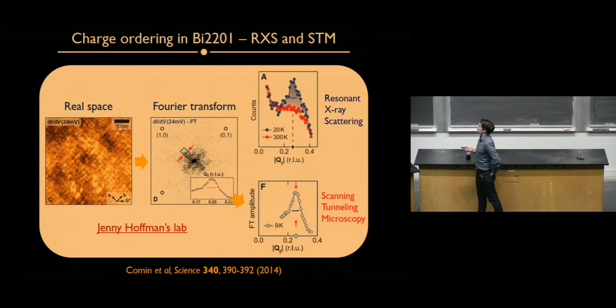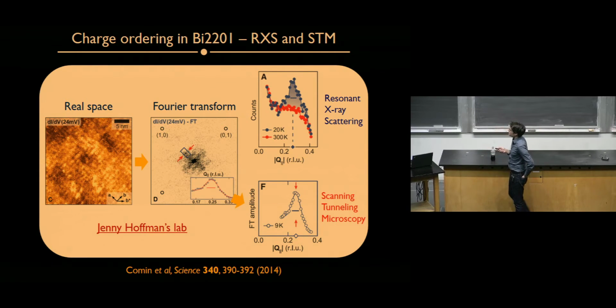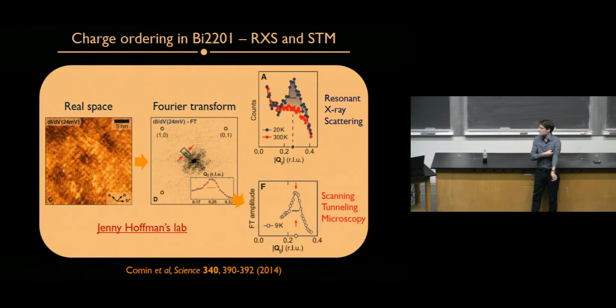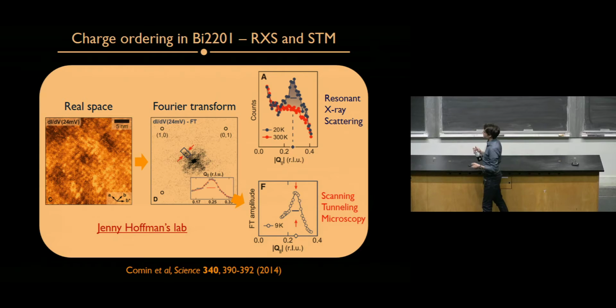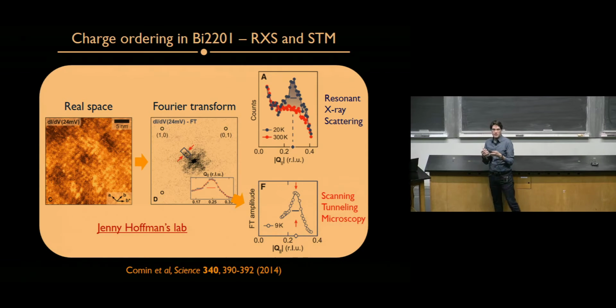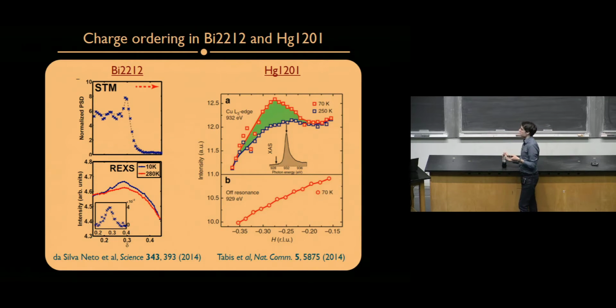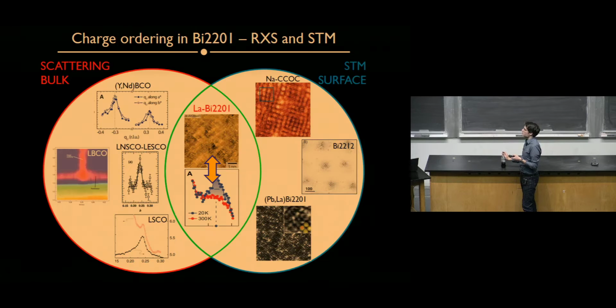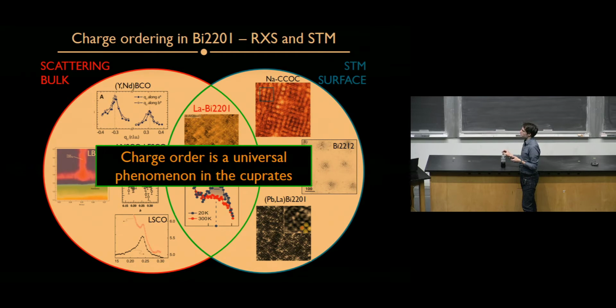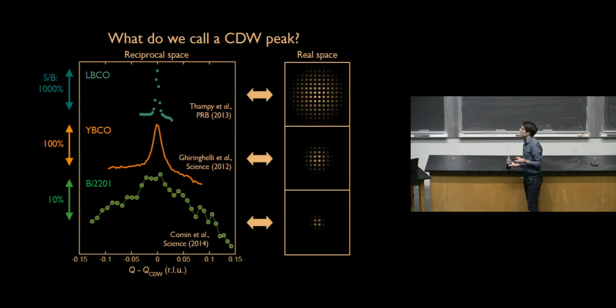And we did this measurement using scanning tunneling microscopy. If you take the Fourier transform of the real space data from scanning tunneling microscopy, then you see a peak which is at exactly the same position as the peak we measure in scattering as a function of momentum. So this confirms that this phenomenon, as was observed previously in real space, is the same as we can now observe in reciprocal space. This has been seen since in other compounds, so it has now been proven to be a really universal phenomenon for the physics of the cuprates.